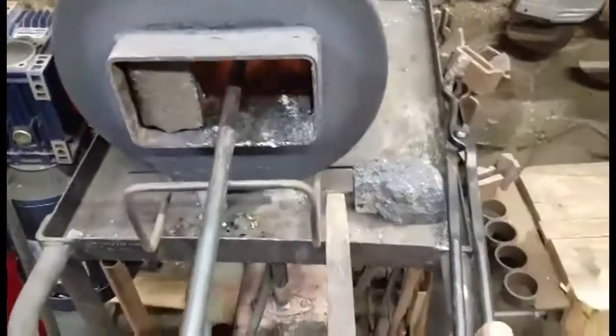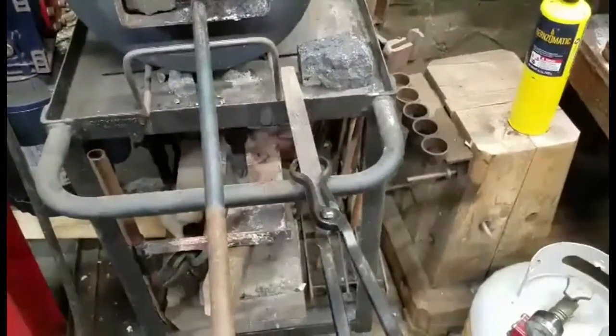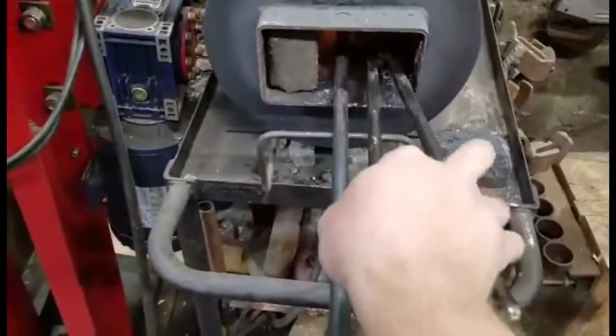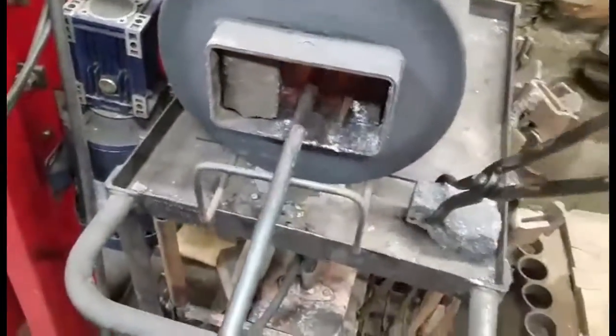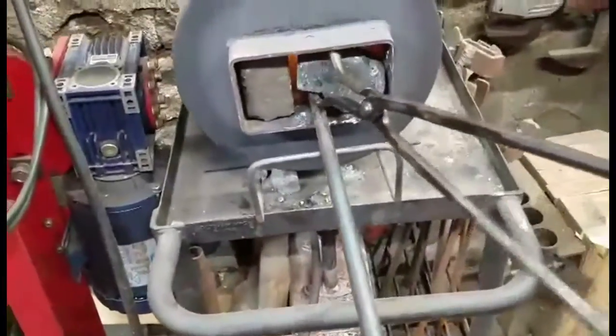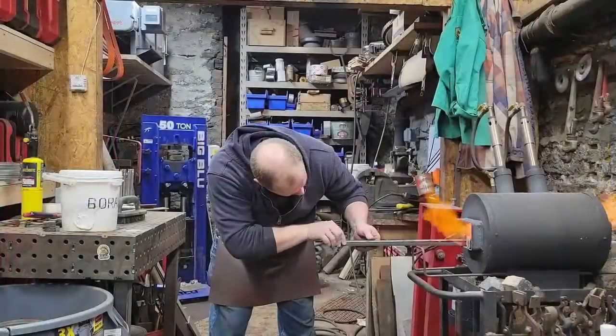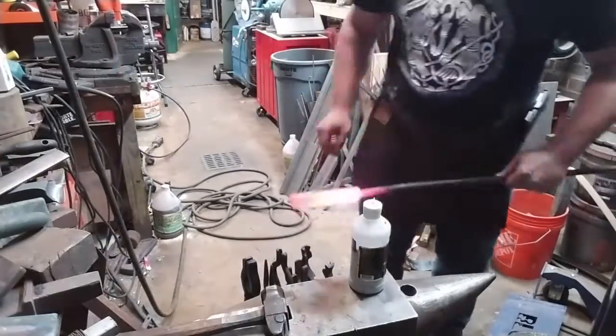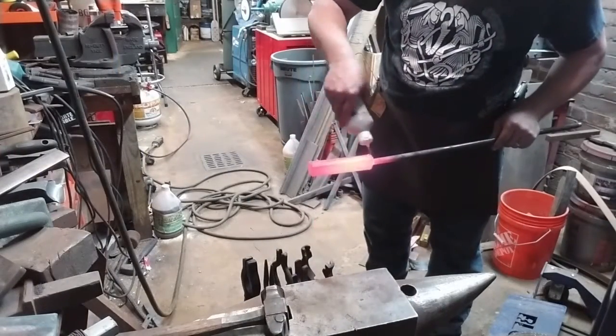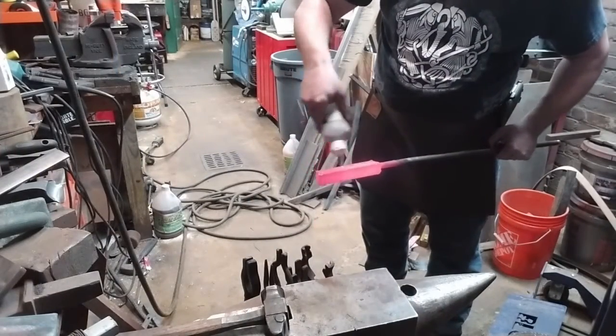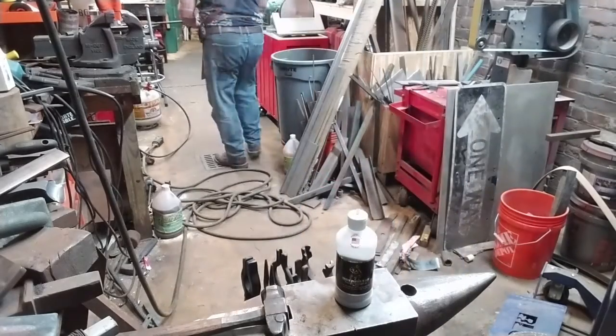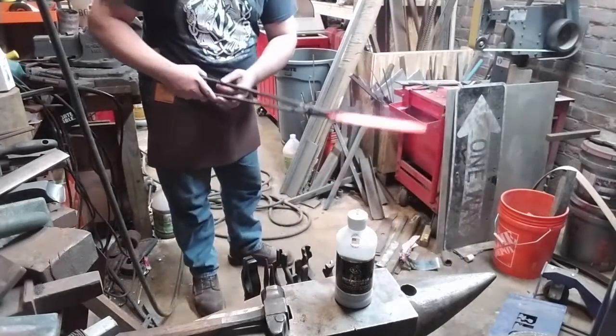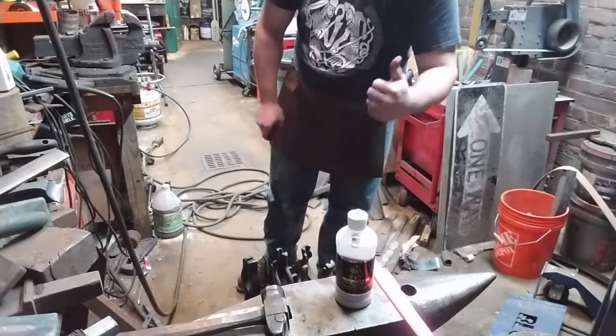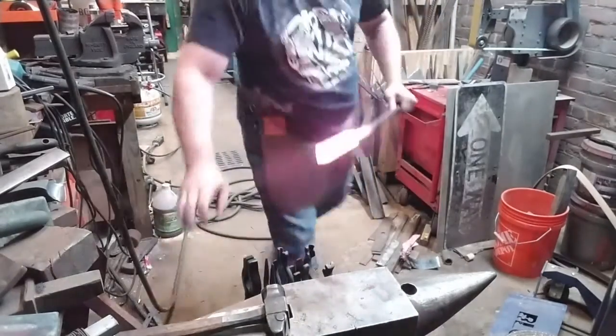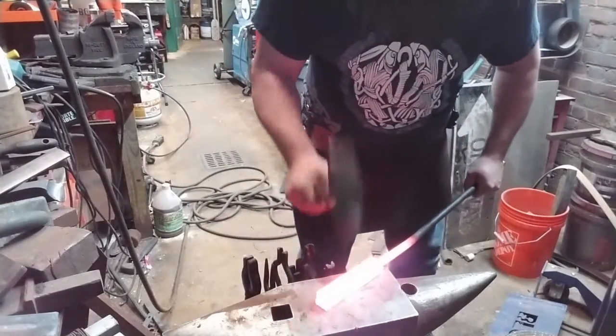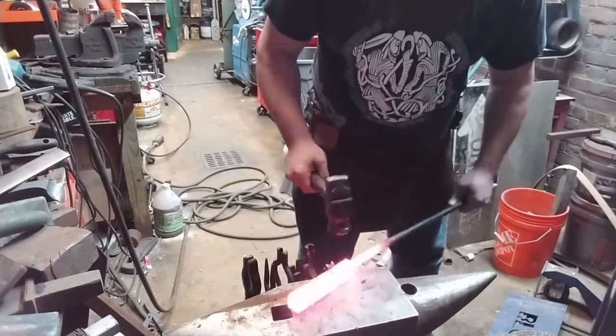And here's our billet, our pattern billet, and here's a file as additional donor material. Now the file is very hard right now, so we're going to leave it in the fire for a little while and let it soften up. Here I'm using Iron Mountain forging flux, which I highly recommend. It's absolutely fantastic. There's the nice and hot file. We'll set that off to the side for a while and come back to it later.